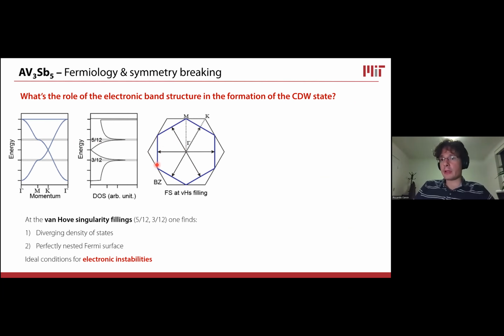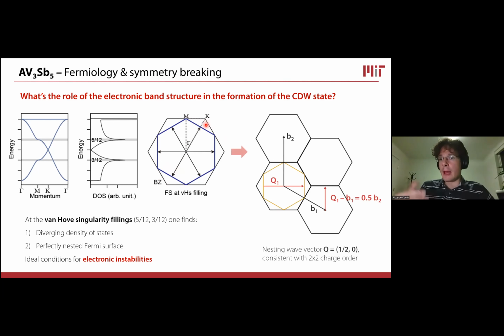So the Fermi surface looks like a perfect hexagon, which means that the flat portions of the Fermi surface that are facing each other are perfectly nested. And most importantly, the vector that nests these flat portions of the Fermi surface at the filling corresponding to the Van Hove singularity is exactly equal to the wave vector 1/2 0. And so at these Van Hove singularity fillings, we have a diverging density of states. That's a good starting point to have symmetry breaking. And then we have a perfectly nested Fermi surface as well. So there can be an additional reason for the system to want to order at a specific wave vector, which is the one corresponding to the nesting conditions.